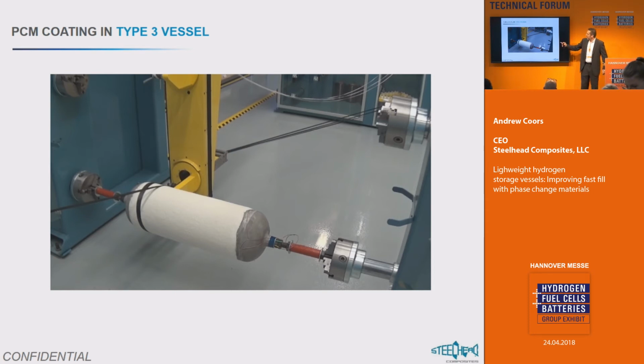Here's an image of the tank. You can see the aluminum liner, and we have the polymeric PCM. It's got the phase change material, the microencapsulated, in a painted-on surface that we put over the tank. And then we reinforce it with the carbon fiber. So in theory, the aluminum would dissipate the heat across the vessel, the phase change would happen in the material, and we would lower the temperature as we're filling quickly. And that's what we saw.